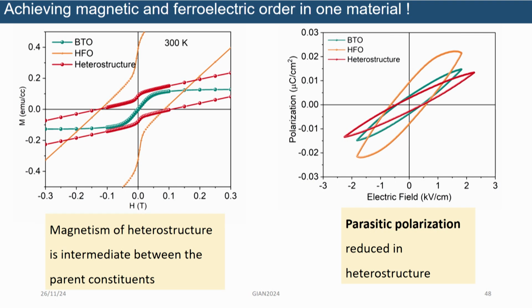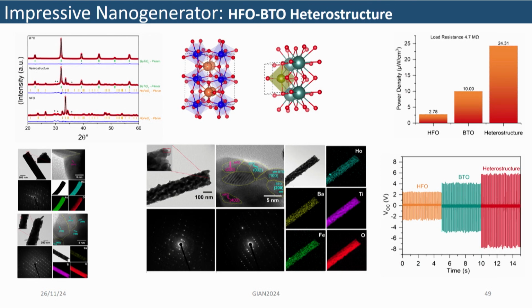we compared. So, you see the magnetism of the heterostructure is actually intermediate between the parent constituents. HFO is a highly magnetic material while BTO is not. So, in the heterostructure we could get something intermediate which was expected. Similarly, we could get the polarization, and then further we checked other parameters which were well in agreement, and then you see we calculated the power and voltage generated. So, HFO is generating up to 2.5 volt, BTO is generating too, but when you combine them the performance is enhanced, right. And similarly, the power density is also more than double that of either parent compound.